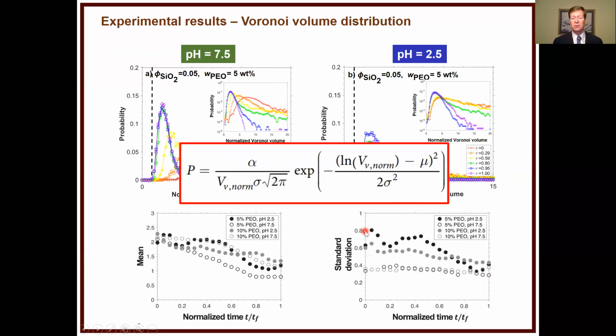Now for the samples that were gel, that's completely different. The fitting for each one of those times is completely different. And again, you could average over many samples and you see that it simply is not monotonic. It will change. The structure is very complicated. It has this history of drying essentially. But at the very end, it starts coming down within range of what you'd find in that chemical-like drying process where the particles are not attractive.